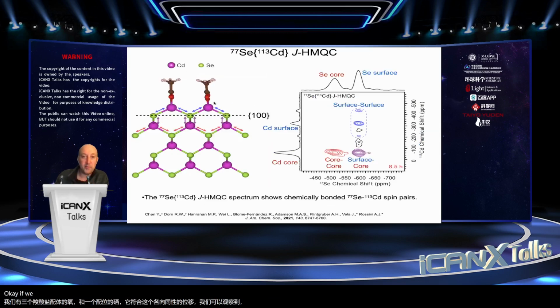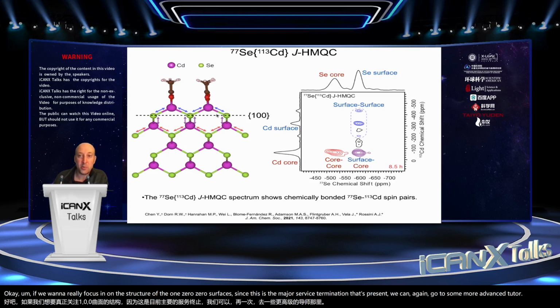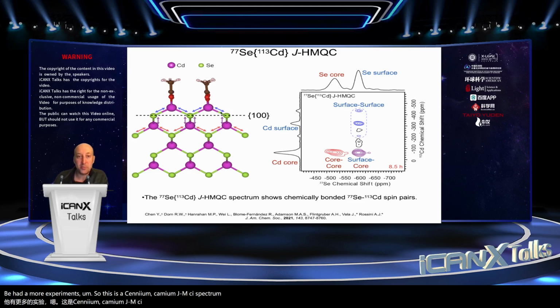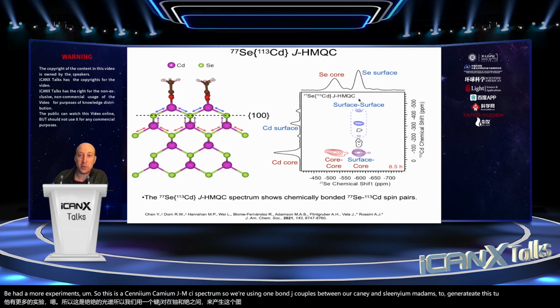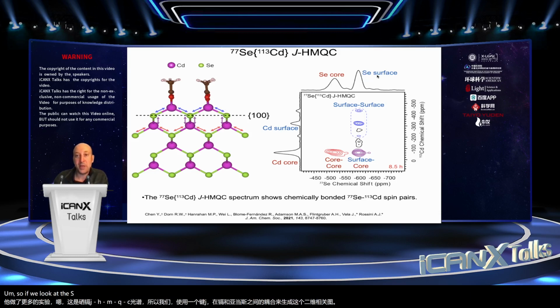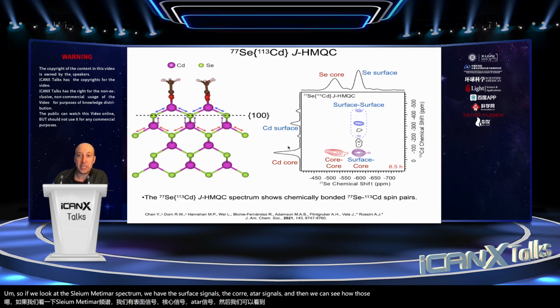Okay, if we want to really focus in on the structure of the 100 surfaces, since this is the major surface termination that's present, we can again go to some more advanced 2D NMR experiments. So this is a selenium cadmium J-HMQC spectrum. We're using 1 bond J couplings between our cadmium and selenium atoms to generate this 2D correlation map. If we look at the selenium NMR spectrum, we have the surface signals, the core NMR signals, and we can see how those selenium NMR signals correlate back to the cadmium. The first connection we can see is surface selenium connected to surface cadmium. That's exactly what we'd expect because those should be connected by a covalent bond.